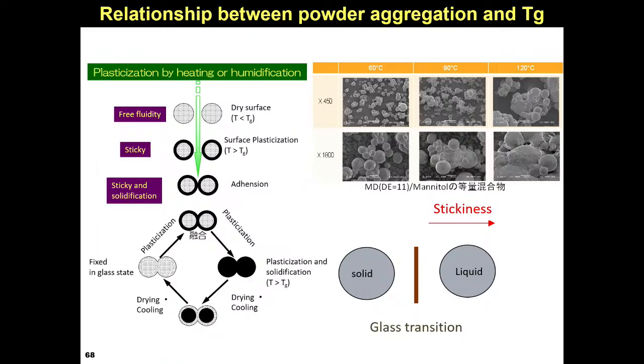Glass transition temperature is the boundary temperature between one particle and aggregated particle. For example, this is maltodextrin and mannitol spray-dried powder, kept at 60, 90, 120. At 60, we can see the particles. But at 120, we cannot see the particles. So glass transition affects the flowing properties of the powder, the physical properties of powder.